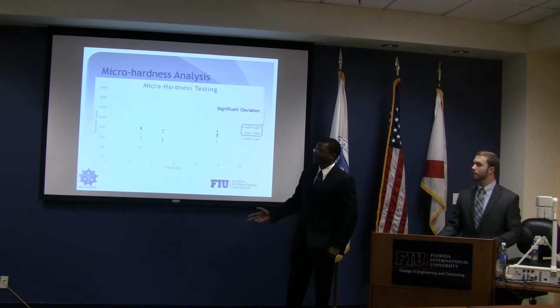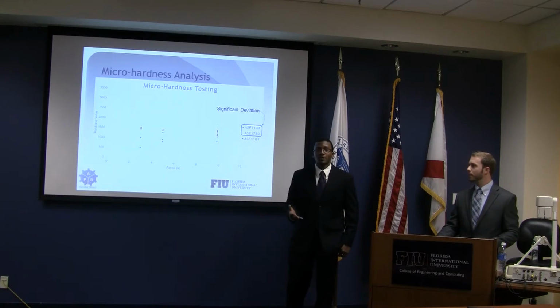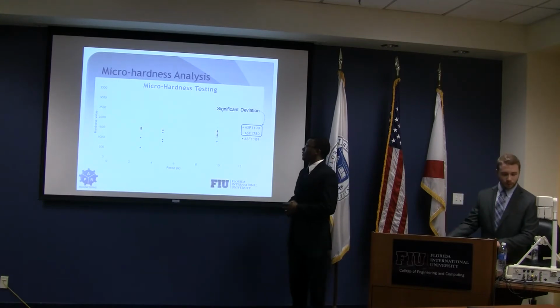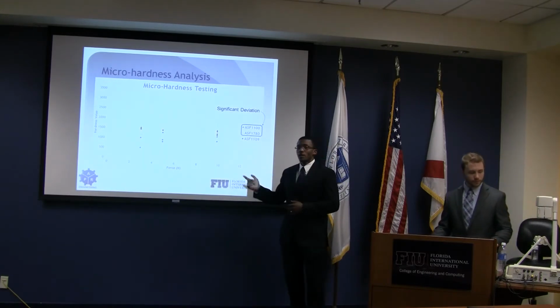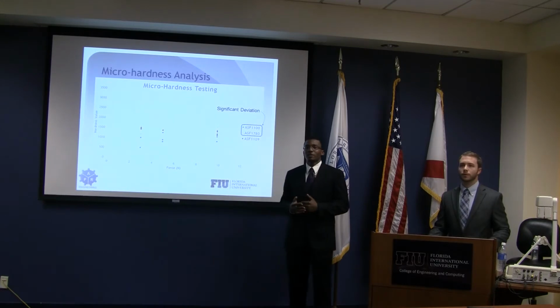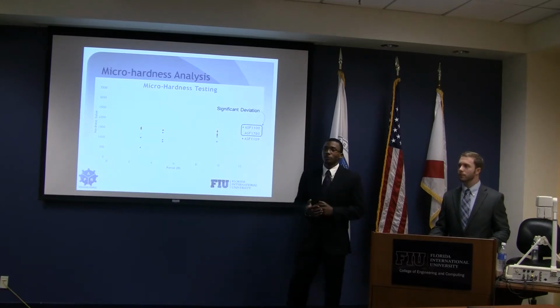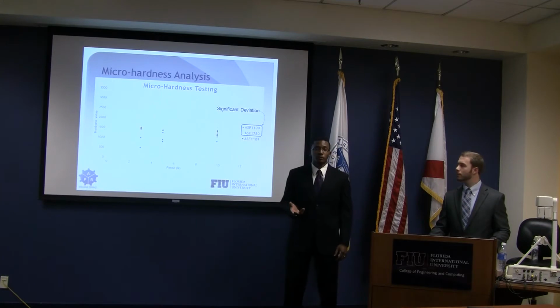We then conducted a Vickers hardness test using 3 different samples. Each of the samples were fired with different glass powders. The most consistent best results were that of the ASF 1109. The other 2 samples had high deviation, which likely resulted from the microstructure and interaction of the silver pins and the regular particles. The 1109 sample achieved a hardness comparable to aluminum, which was our baseline target.